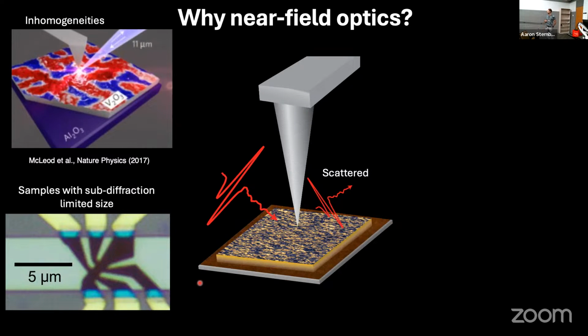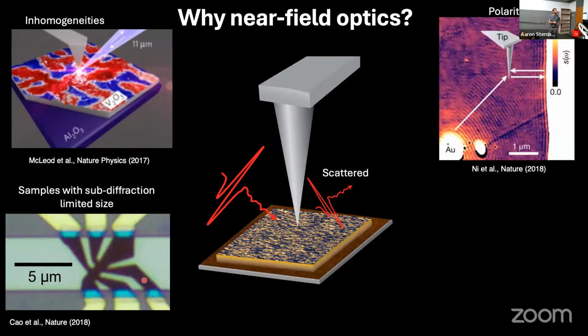The second is that in many cases, especially when you're dealing with 2D materials, the entire size of your sample may be smaller than the wavelength of light that you would like to use to address certain phenomena. So maybe somebody in the audience recognizes this image. This is from the famous 2018 paper on twisted bilayer graphene, where it was revealed that this tiny region was superconducting. And one has to overcome twist angle inhomogeneities to observe these kinds of physics. In this particular device, you can see the entire size of the sample is small. And so if you wanted to look at low energy properties, for example, in the terahertz, this would normally be difficult to impossible.